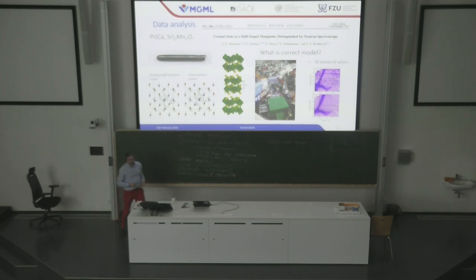Altogether it took about 1 week, and roughly 30 million values were collected. And then the physicists who did the experiment were clever enough to cut this big space of 30 million values to some areas where they expect differences between these two models. They figured out that if you measure at this energy and this particular momentum transfer, you should be able to see the splitting of the band or not the splitting of the band. And based on that, they figured out that the first model is correct. So this is a classical approach.